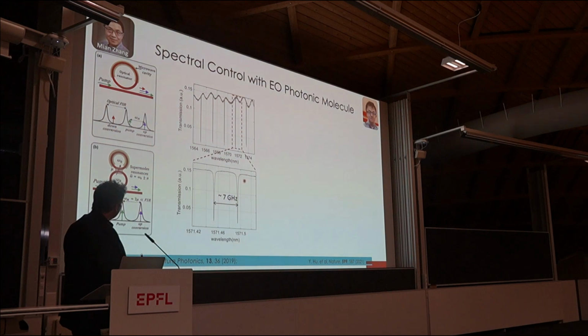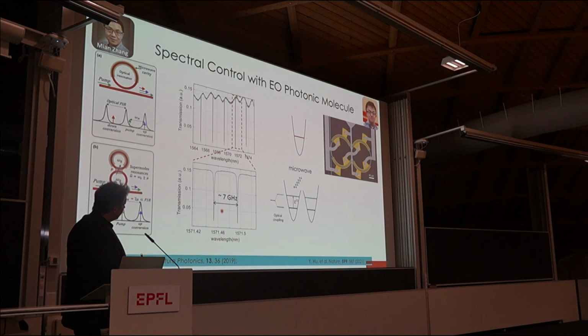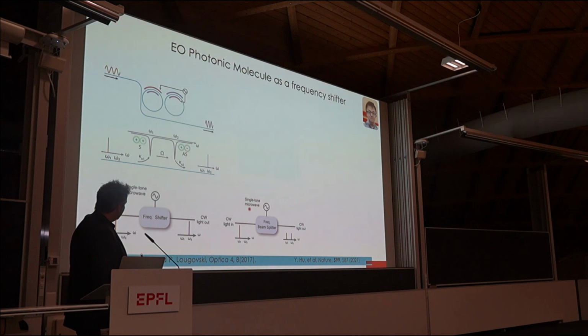And the nice thing about the system is that this splitting we can address, in our case, using electrical signals, because these two resonators are made in lithium niobate. This is how they look. Two lithium niobate ring resonators with two optical waveguides to bring light in, and RF electrodes. The idea is you put light in this optical resonance, apply an RF field, and this light will jump out. And then we collect it from there. And so that's how we shift the color of light. And it can be done with pulses or CW. Maybe I'll just show you a result in the interest of time.